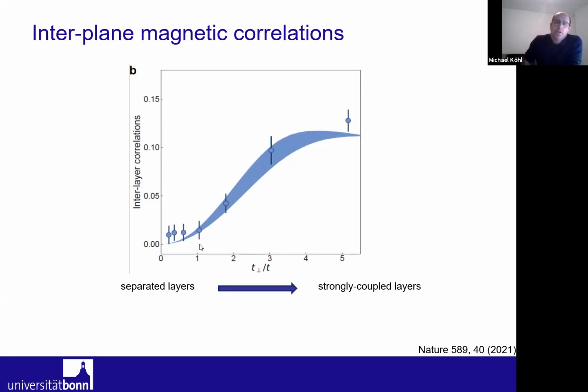You see that for low tunnel coupling, there are no interlayer magnetic correlations. So it's just an uncorrelated mixture of singlet and triplet states. And as we increase the interlayer coupling, these magnetic correlations between the layers start to build up. And if you remember the previous picture, it's exactly the opposite behavior. So that really shows you that there is this crossover between the two magnetic orderings.